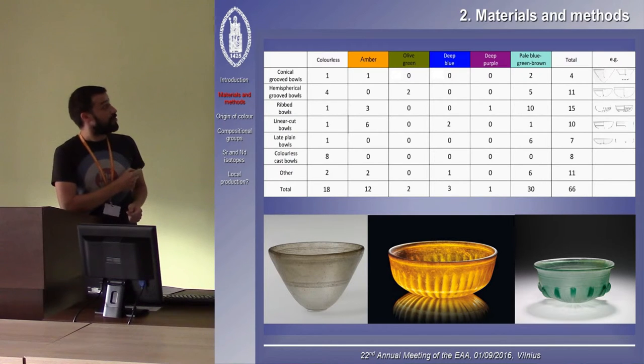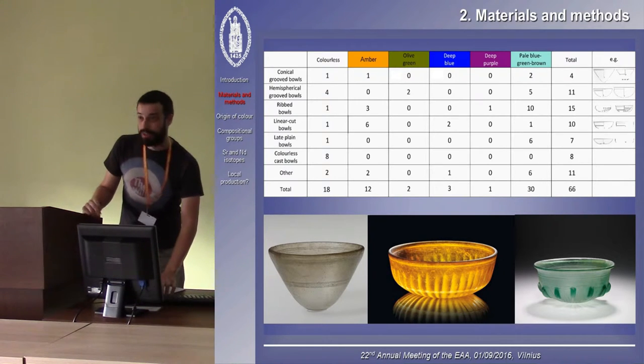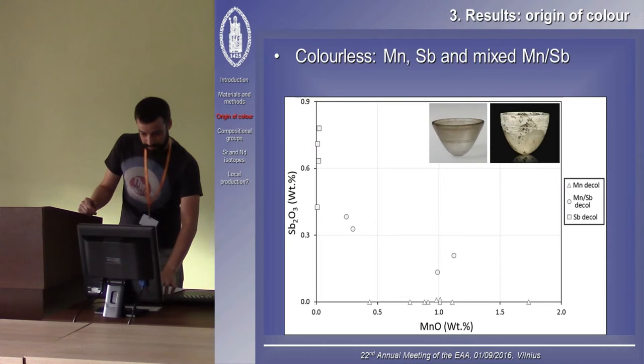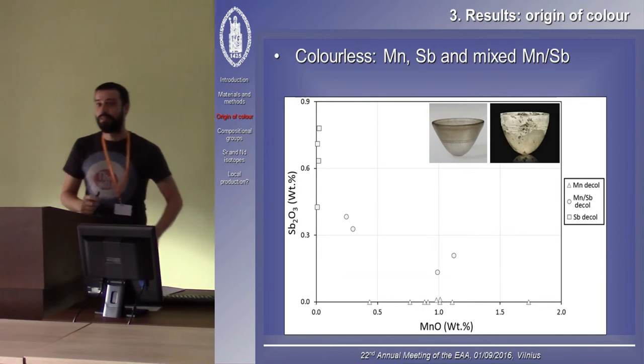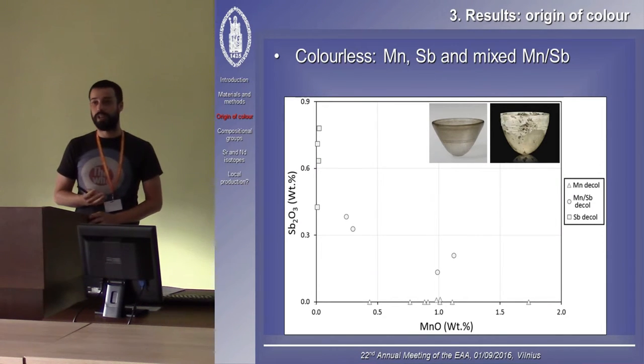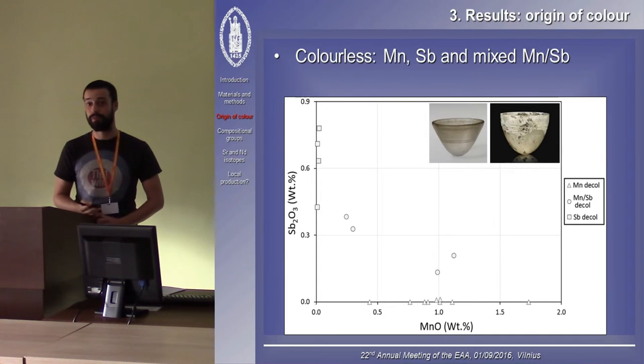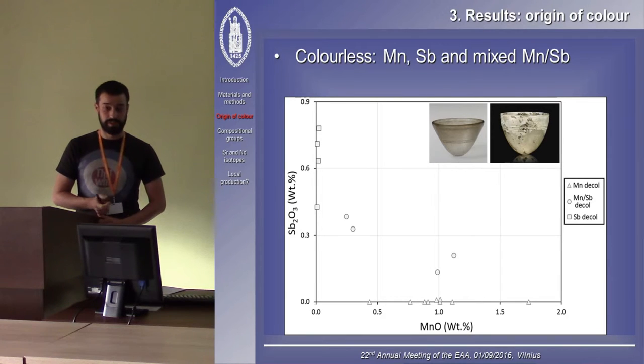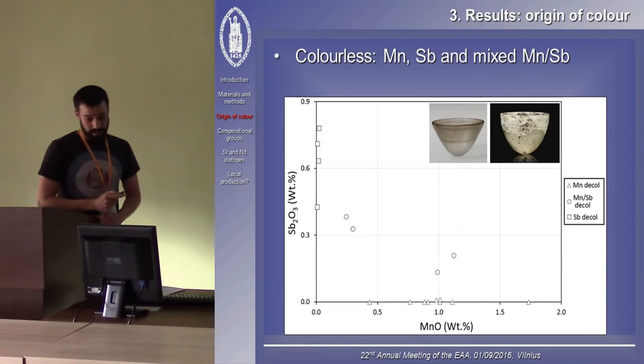I will talk, however, very shortly about the colorless glass, because we're going to need that a bit later. As I said, most natural colored glasses are slightly green or blue due to the iron, but the Romans and other ancient glassmakers could solve this by adding small amounts of manganese or antimony to the glass. These elements would oxidize the iron, making the glass colorless.